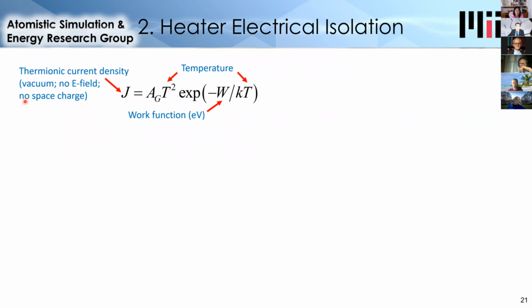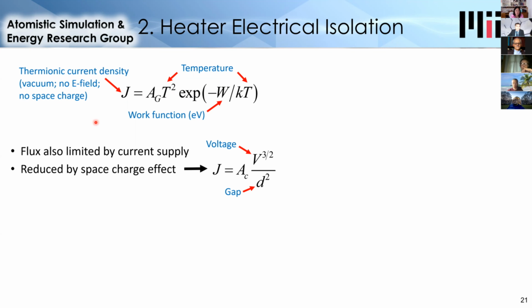Space charge effect is basically when an electron is emitted from a surface, the second electron is influenced by the previous electron. And since electrons repel each other, it's repelled back to the surface. And so the space charge effect is a very important effect that mitigates arcing. The arcing current is also limited just by the current we're providing to the heater. So for example, if you heated up a material not connected to any electricity, it would emit a few electrons, but then become so positively charged that no more electrons could be emitted. But in this case, we're supplying current.